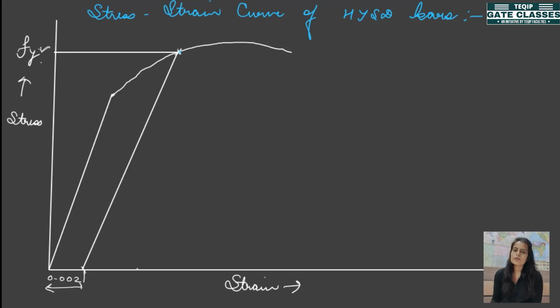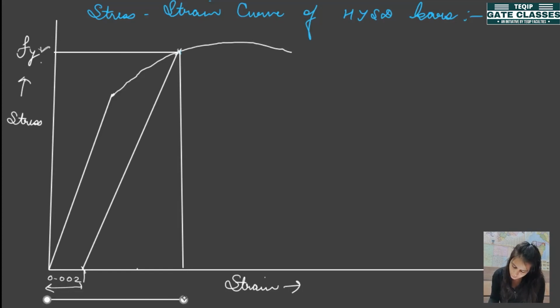Now if I want to find out the total strain corresponding to the yield strength of this material, then draw a vertical line from this point and this will be the total strain corresponding to the yield strength of this material, right? So total strain will be the sum of this 0.002 and this part of the strain. Okay, so we have to find out how much will be this part. This we can find out using trigonometry, as we know that the slope of this line will give us the modulus of elasticity and both of these lines are parallel to each other, so the slope of this line will also be modulus of elasticity and slope is given as the perpendicular upon base.